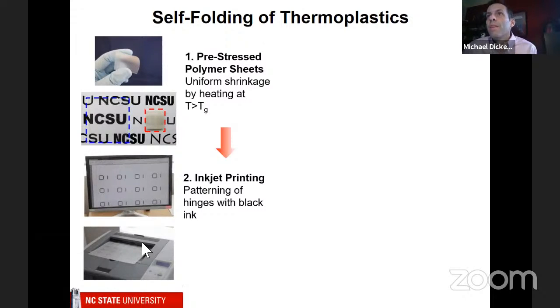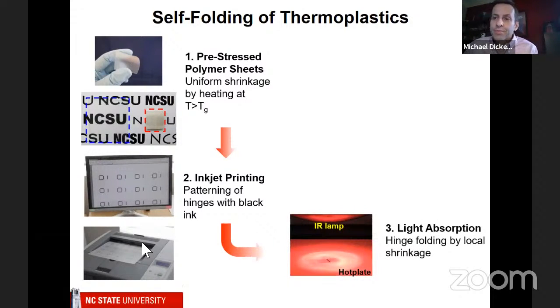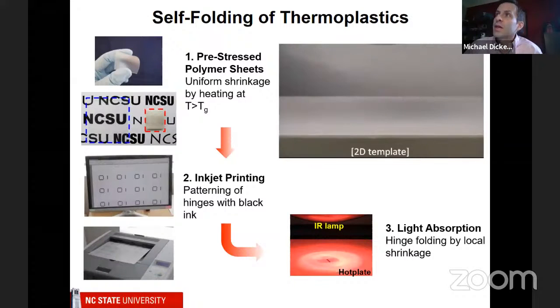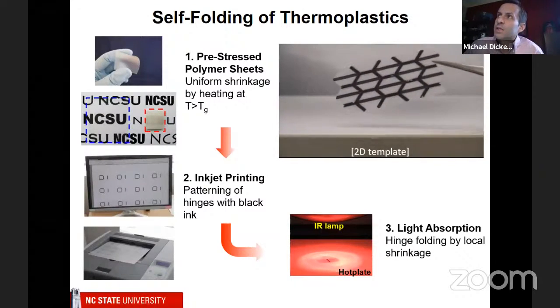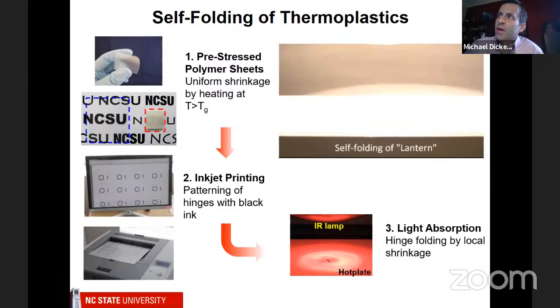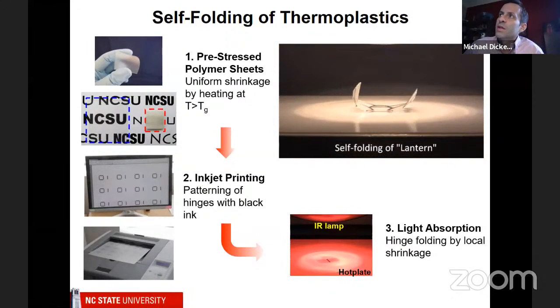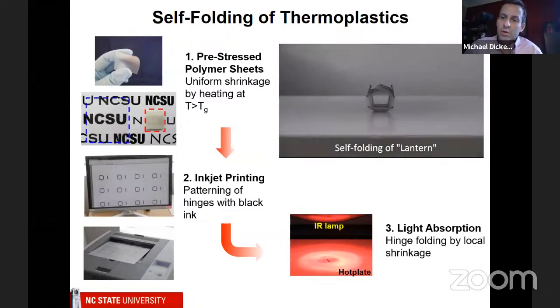Anybody can do this. And so then we shine light. The key idea is that the black region with the ink absorbs the light and it gets hot. And as a result, it shrinks. And when it shrinks, it causes it to fold. Of course, you can put the ink on the top, and you can also put it on the bottom of the sample. Either way, it will always fold towards the ink. So you can see that in this video. This sheet actually has ink on the top and the bottom, and you can see that it folds into a more complex three-dimensional shape.